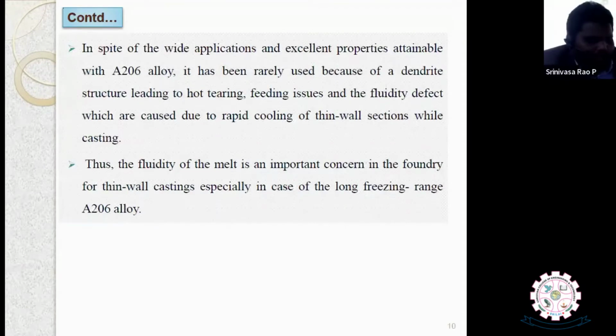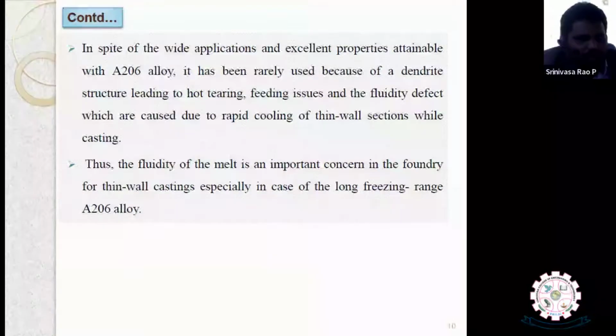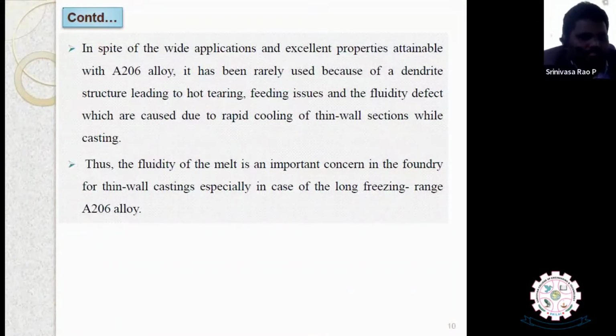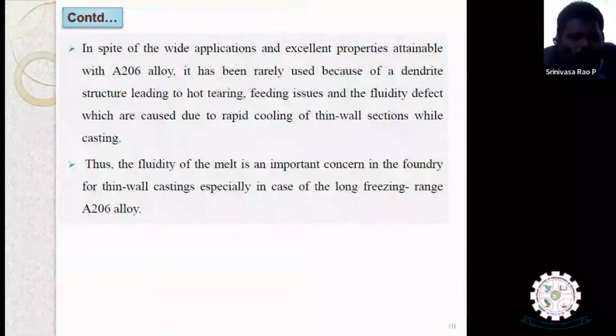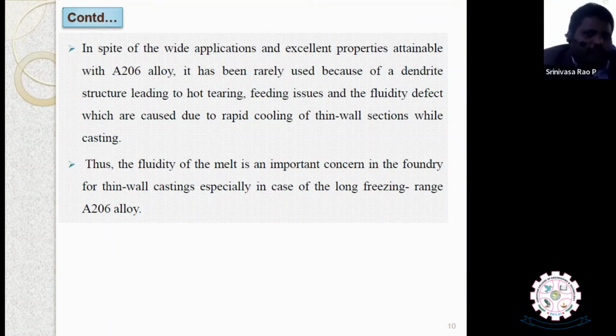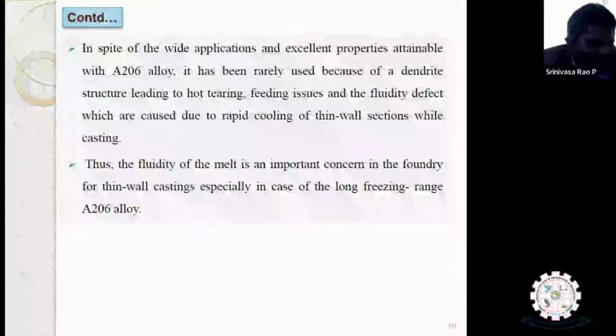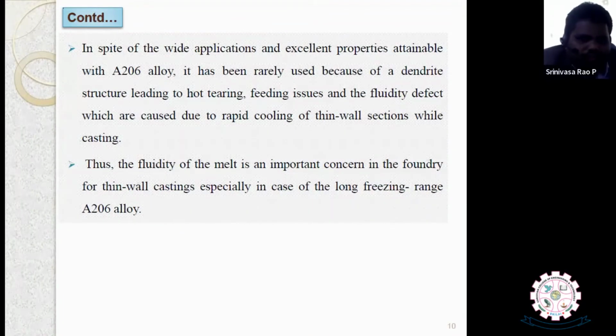We don't require the details of the Taguchi method. After making the sand mold, we are going to talk about the A206 alloy, that is, aluminum copper alloy, which has been cast using the optimized sand properties. Optimized sand means we have taken certain parameters and made the green sand mold, and in that mold we have made the A206 alloy casting. The problem with the A206 alloy, aluminum copper alloy, while casting is that the main defect we found is that the fluidity of the melt is very important. Misrun is the major defect in the A206 alloy.